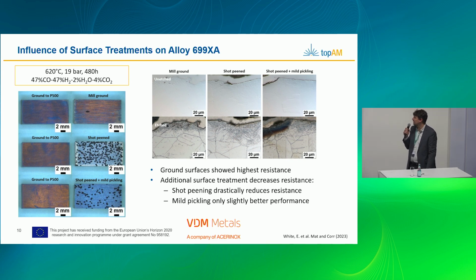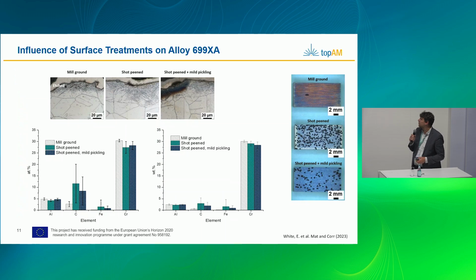Now you can already see those pits that show clearly the metal dusting, and the same is true with shot peening and mild pickling. So when we look below the surface on the right, in the cross sections, you can see the mill ground, the shot peen and the shot peened and pickled. And here you can already see the cross section of this pit where the attack was. You can see some deformation below the surface, but that should usually not be such a big problem for the corrosion and metal dusting behavior.